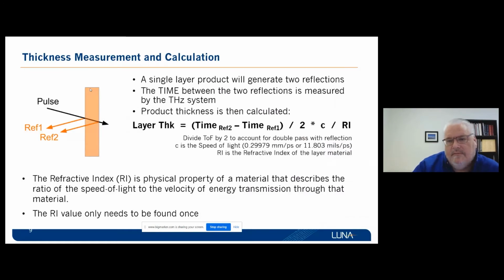So one of the primary things that we measure is the thickness between layers and structure, so that you can calculate that essentially by measuring the time of flight between the reflection of two layers. And again, we can measure down to easily less than 10,000th of an inch, and actually down to microns, depending on the material. And this is because of the extraordinary high time resolution of the waveform. We're literally measuring the speed of light as you're going through millimeters to microns thickness of layers of material, the difference in that.